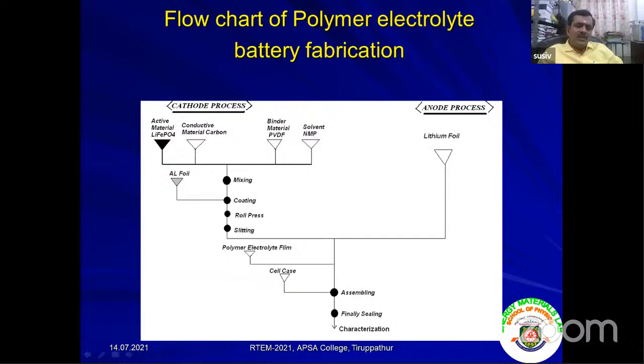Using that electrolyte, with the cathode material or anode material, whatever it is, here I am giving an example. We can have the active electrode cathode material, namely LiFePO4, added with conductive carbon, Super P, and binder PVDF, polyvinylidene fluoride. All are dissolved in the solvent N-methyl pyrrolidone and mixed together using the homogenizer. I will show the video of it, and it has been coated on an aluminum foil. After that, it is roll pressed and slitted into circular shapes.